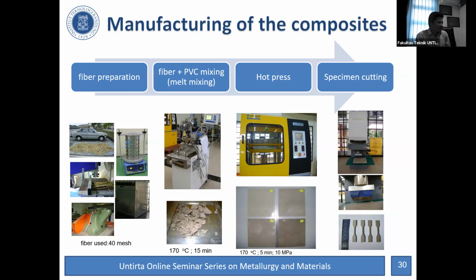Okay. So you chop the fiber into little pieces, and then you mesh the fiber. We get the fiber to 40 mesh, and we oven-dry the fiber to make sure that it is dry. Then we mix the fiber with PVC in a melt mixer at 170 degrees Celsius for 15 minutes, and you will have these granules. Then we compress it at the same temperature, and we will have this kind of plates.